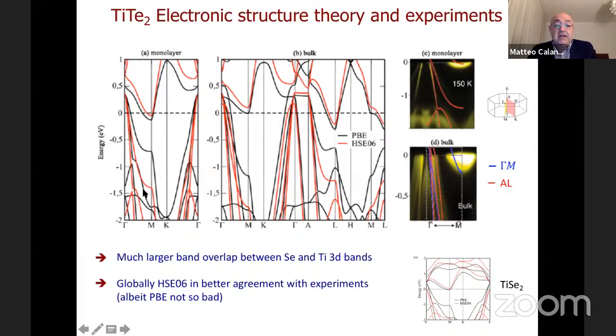So even if titanium ditelluride is perfectly isoelectronic to titanium diselenide and is a perfectly compensated metal, it turns out that the tellurium band, due to the level alignment between titanium and tellurium, has hole pockets and is partially empty, and the titanium band, on the contrary, is more occupied.